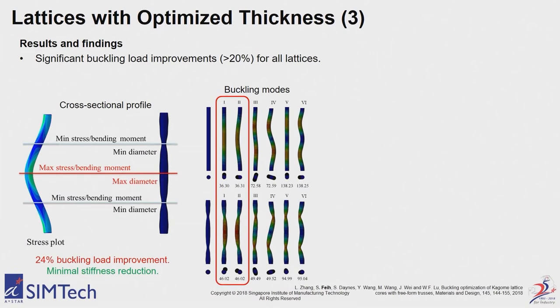So the results here that we basically see is a buckling, so a single rod under buckling, and we can see that where the bending moment is the highest, we're actually trying to make the structure thicker, and where the bending moment is the smallest, we're making the structure thinner. The buckling loads as a result go up for the same volume, and we're getting significant buckling load improvements. As an engineer, I say anything larger than 20% is pretty good for the same weight.